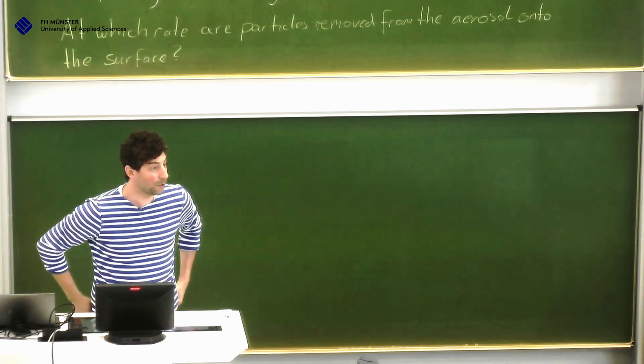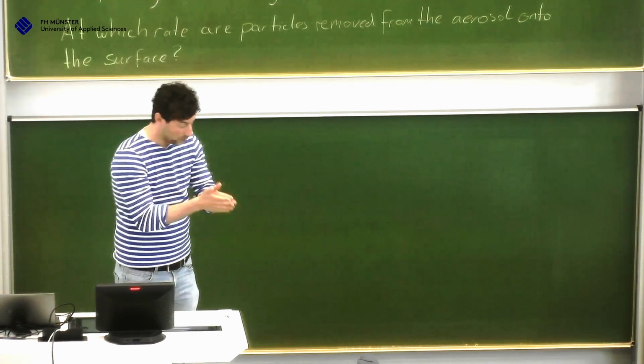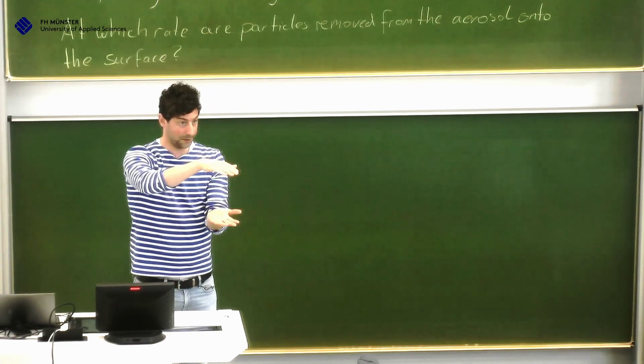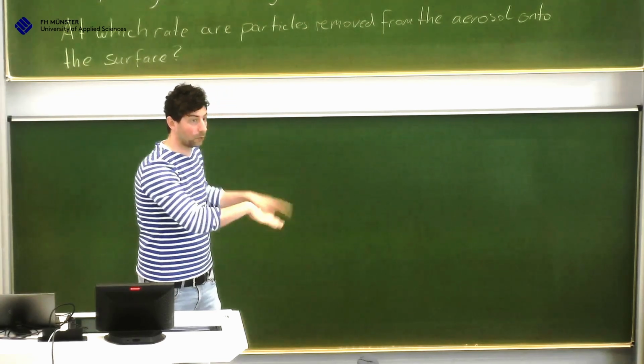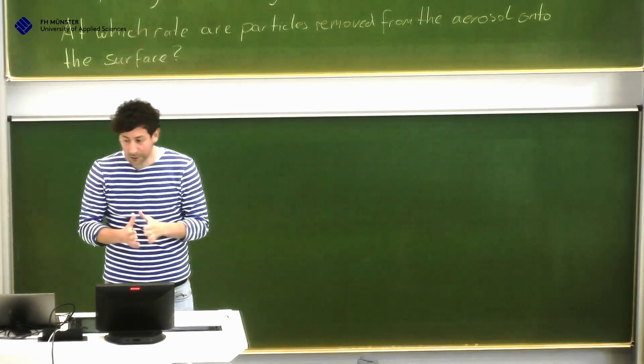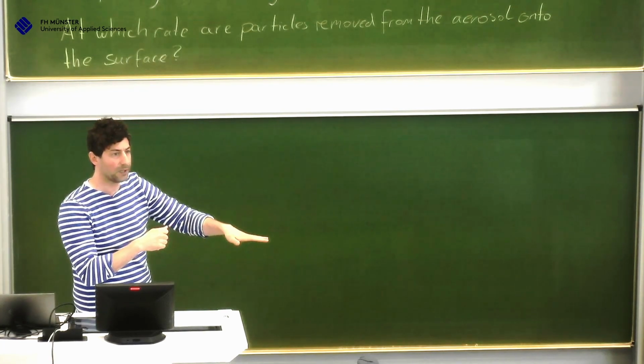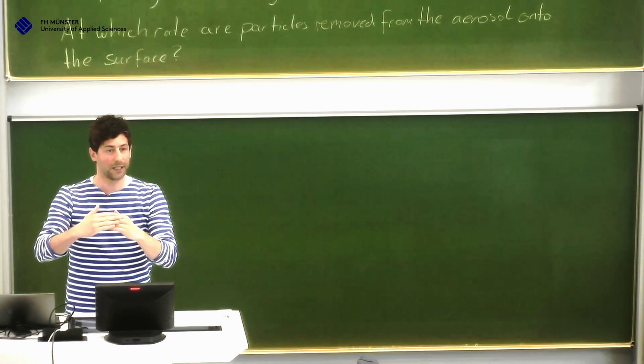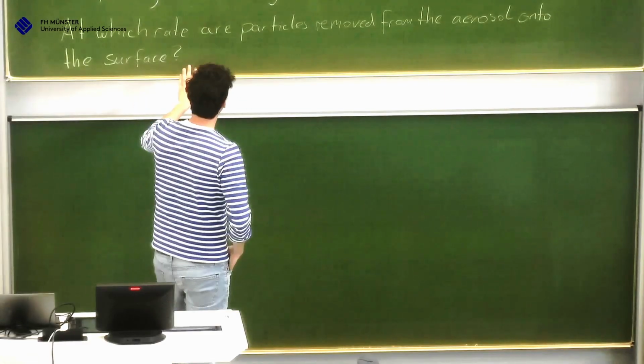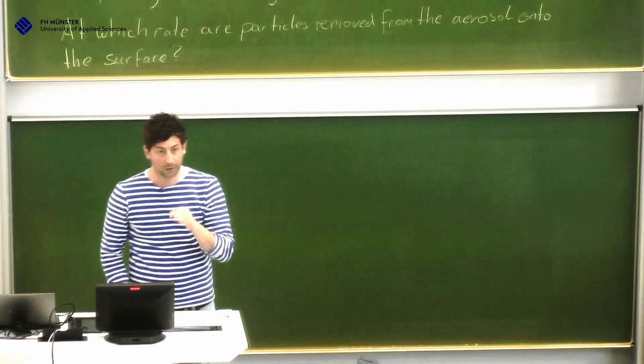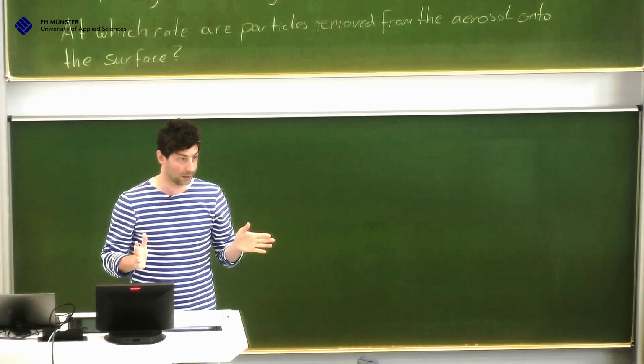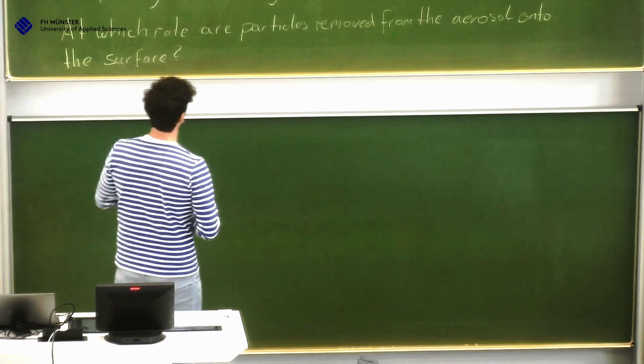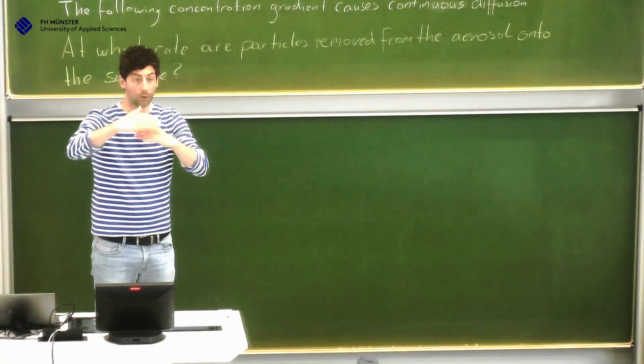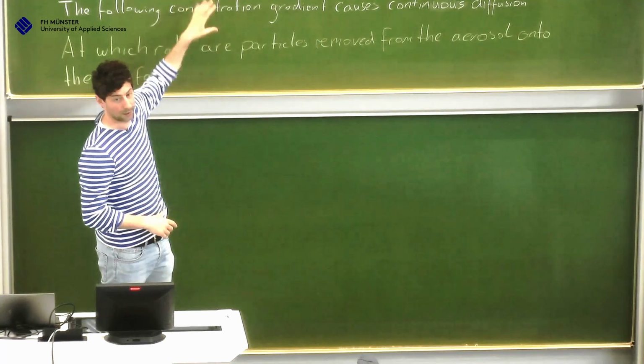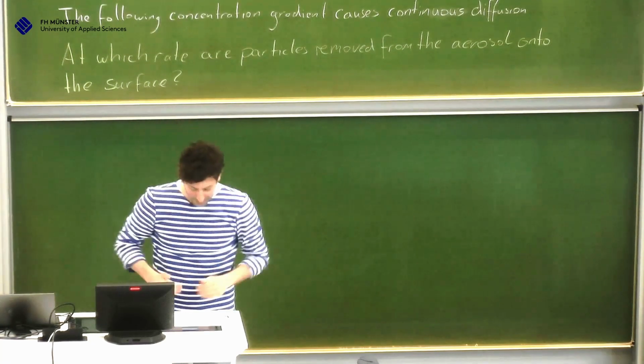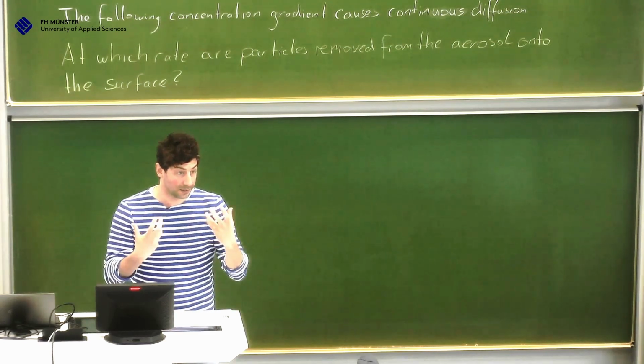Exactly, perfect. So it's basically right what you're saying, but in coating you grow a material. And this growing we completely neglect here, okay? Here there's no growing. Once the surface is touched, it's gone. So for coating, you could calculate how many of them I will have on the surface, but then you have to make an additional calculation: how does the layer grow? That's not in the picture here. For me, it's really important for all the concepts we're discussing that you can describe the models very clearly. So if you say this works for coating, then I want the explanation that in coating we have a growing layer, and this is not in this model here. You know this from particle technology, that I really want the importance of the models. This is really something you should be aware of.